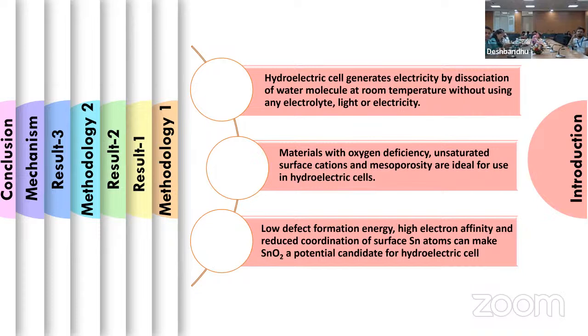So any material that is to be used for hydroelectric cell application must have three main characteristic properties. First, the material should be oxygen deficient. Second, it should have unsaturated surface cations, and mesoporosity. So why tin? Tin is a material with low defect formation energy, high electron affinity, and it has reduced coordination surface of tin atoms, which makes it a potential material for hydroelectric cell applications.